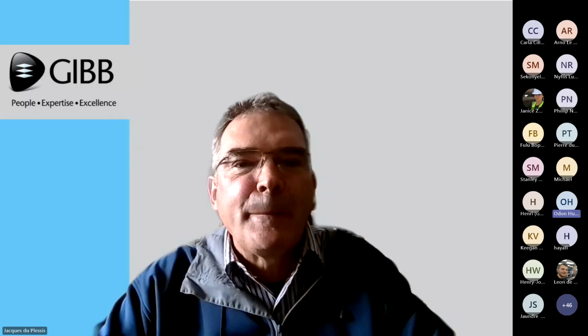Hi, this is Odon from Zutari. I was just curious. You mentioned the water stops and the trend to go to water stops on the face. What water stops did you end up using at Bedford Dam as the upper one? Yes. So we had a copper water stop, a 1mm copper plate with a central rib at the back, and in the center we had a 250mm rubber water stop. But we experienced a few problems on site with getting honeycombing underneath the rubber water stop.